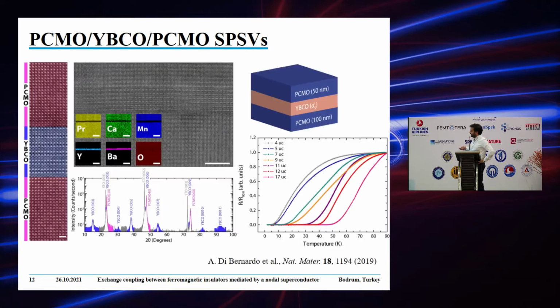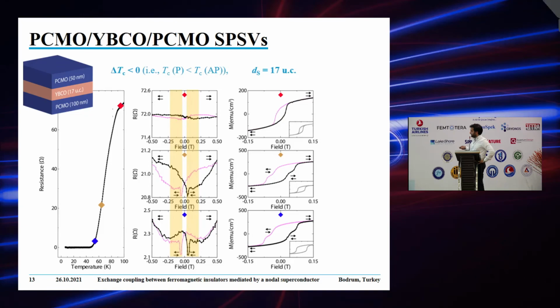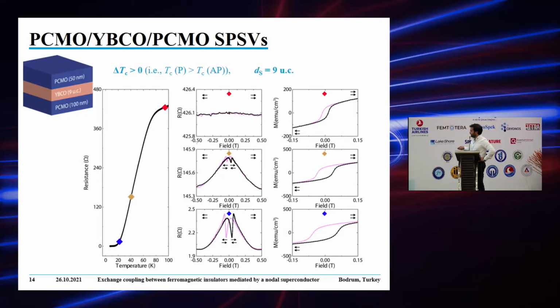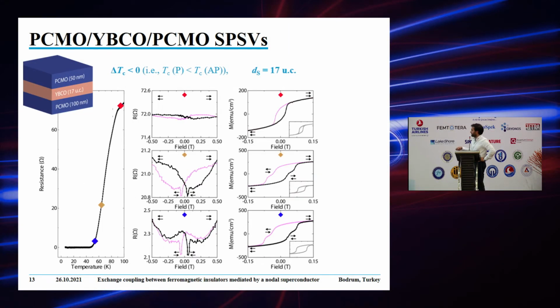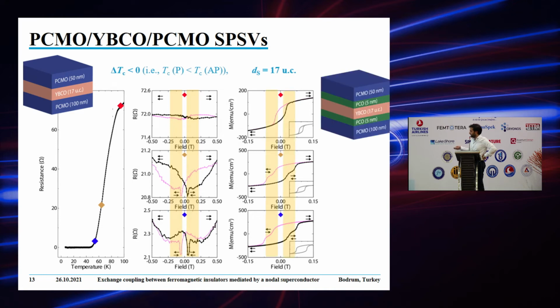And what you can see here is that the minimum in resistance, which means the high TC state, is the antiparallel state. And when the antiparallel state is the high TC state, so the energetically favorable state, we observe the same thing as in the Cambridge experiment I showed earlier. So there is the emergence of this mismatch, sort of an increase of the region where the two ferromagnetic layers are antiparallel.